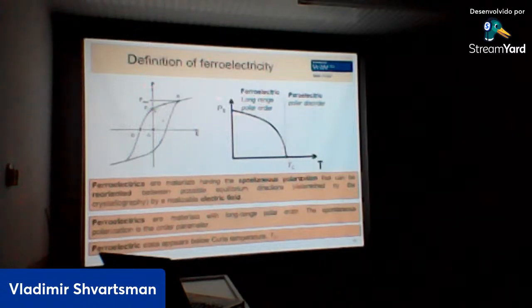Ferroelectrics, by definition, are materials that have a spontaneous polarization. So not only induced polarization like in normal dielectrics, but even in the absence of an electric field they possess a polarization, the remanent polarization P_R. This polarization can be switched by application of a specific electric field, which is called the coercive field, and we can change the direction of polarization. Typically for ferroelectrics, we observe such a characteristic polarization hysteresis loop. The ferroelectric state usually occurs below the so-called Curie temperature, where our material has a structural phase transition, and in some cases this transition is accompanied by the appearance of long-range polar order, ferroelectricity. Above the Curie temperature we have the so-called paraelectric state, a polar disordered state, and below the Curie temperature we have the polar ordered ferroelectric state.